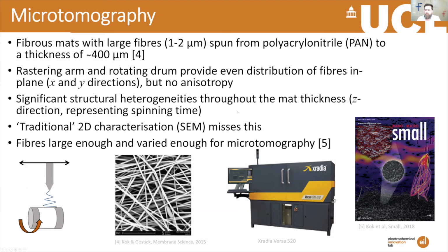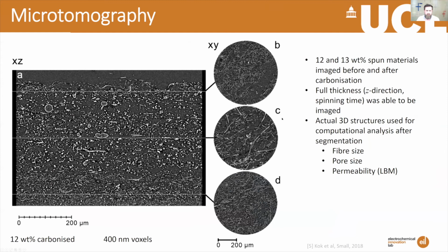But in this case, he rastered across a rotating drum target, and so in doing that, you can increase the rotational speed and bring some anisotropy into the direction of the fibers. Okay, so in the X and Y direction, normally you wouldn't have any difference. They're kind of randomly aligned, but if you rotate fast enough, you can force an alignment into that direction. You do, however, get some heterogeneity through the thickness of the mat, because the fibers are put down in time, and that is the equivalent of thickness. And so often 2D characterization, you can see an SEM there, sometimes misses the heterogeneity in these materials. And in this case, that was definitely what happened.